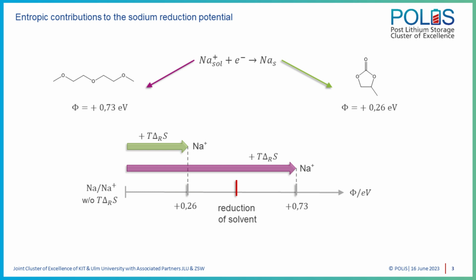These findings can now explain the differences in the SEI in the investigated systems, which are reported in the literature. These differences can be illustrated by a potential scale, where the reference potential is the sodium reduction with purely enthalpic contributions. And for comparison of both systems, we assume that the solvents are decomposed at the same potential. The higher entropy contribution in diglyme would then shift the reduction potential of the sodium ions to a potential above the decomposition potential of the diglyme molecules. And the contribution of entropy would thus result in a relative stabilization of the diglyme molecules compared to the sodium reduction.